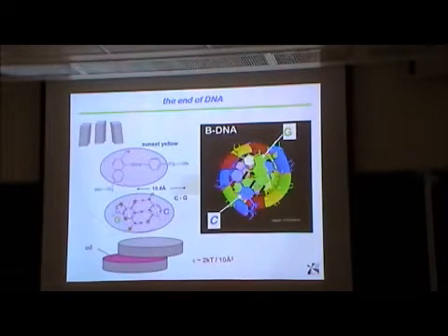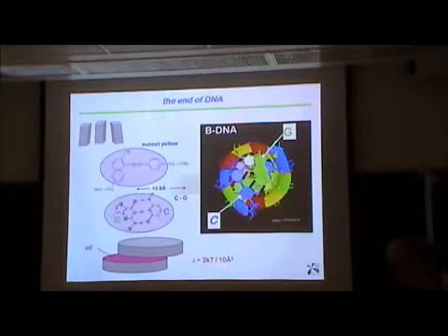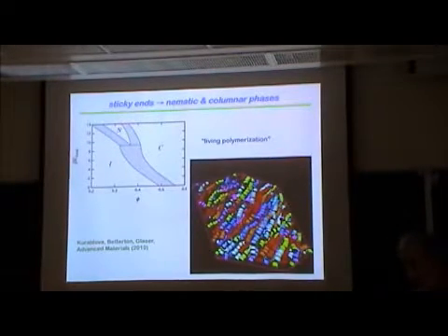The reason for that is that DNA has sticky ends. The bases are exposed at the end of the DNA. This compares a GC base pair to sunset yellow, which is one of the chromonic liquid crystals. They're about the same. So this end is not very happy being exposed to water, and so there's an end-to-end attraction between the oligomers.